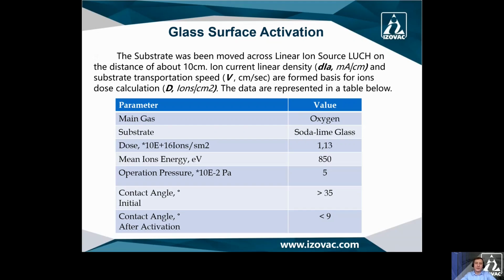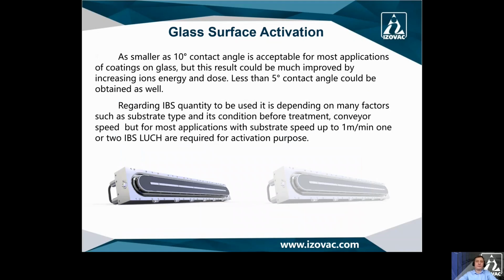Oxygen was used as a main gas. Soda lime glass was used as a substrate. Here is the dose of ions received on a substrate, mean ion energy in electron volts, and operation pressure. Contact angle before treatment was more than 35 degrees. After activation, it decreased to less than 9 degrees.